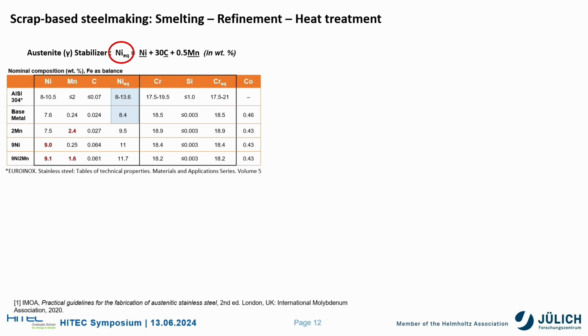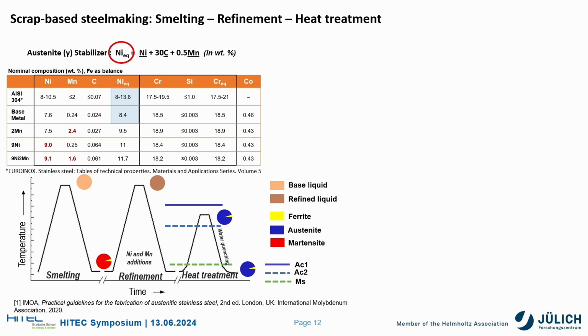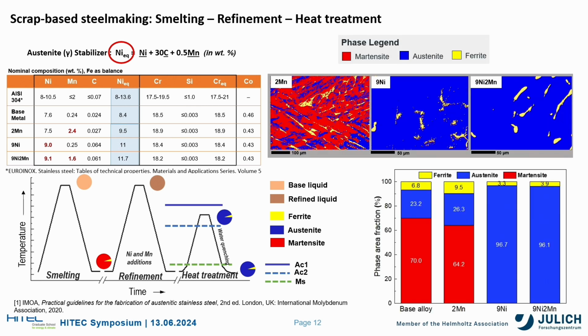Hence, we did refinement experiments, in particular alloying, such that we increased the manganese to around 2%, nickel to around 9%, and nickel and manganese to around 9 and 2% respectively, all with the intention of increasing these nickel equivalent values. So results have shown that the addition of manganese did not help stabilize the austenite, as you can still see with this red phase map here. But the addition of nickel, and both nickel and manganese, have yielded blue austenitic phase maps with small amounts of these yellow ferrite phases, which is about 4%.